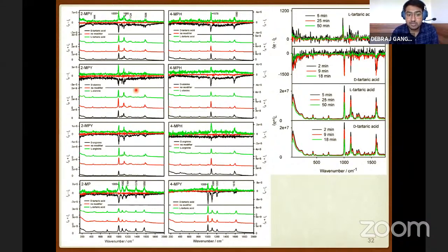And we have also tested for the reproducibility of our results. This set of spectra that I'm showing on the left side of my slide were recorded in my laboratory where I work in IOCB Prague. And we have reproduced these spectra in another instrument, which is in another city in the Czech Republic, in Olomouc. They have a very sophisticated Raman optical activity instrument, and we have reproduced the same spectra in that laboratory. So we have checked the three most important aspects for recording surface enhanced Raman optical activity, which were not done before this ever.